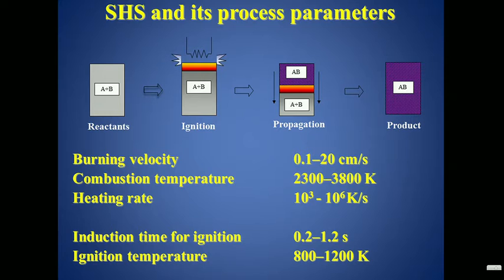As far as SHS is concerned, typically you have a reactant, then you ignite the reactant powders, and you get the product in a very fast way through a propagation front. At the very end, you can get very high velocity, and also a very small induction time for ignition. It is very well known that SHS powders are very good in sintering.